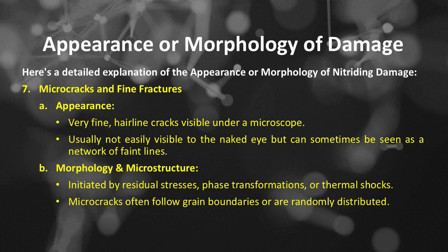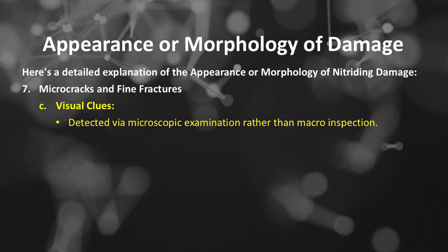Morphology and microstructure of microcracks and fine fractures: they would be initiated by residual stresses, phase transformations, or thermal shocks. Microcracks often follow grain boundaries or are randomly distributed. Visual clues: detected via microscopic examination rather than macro inspection.